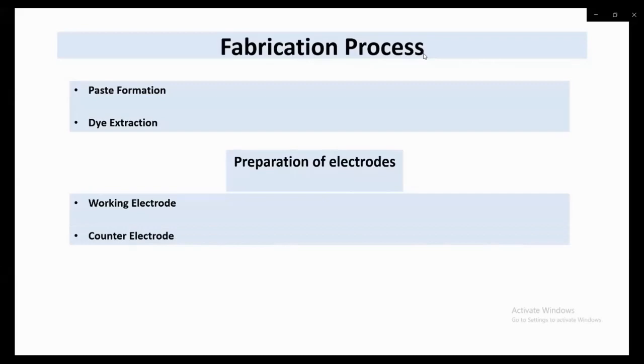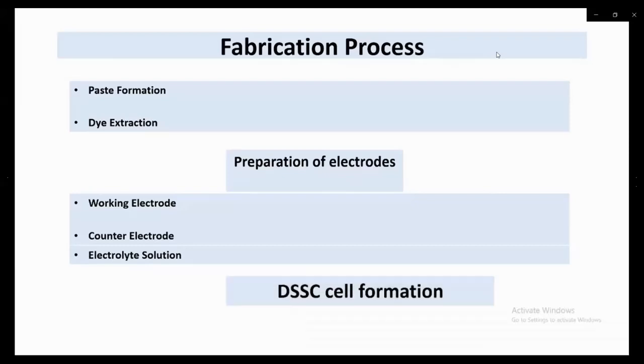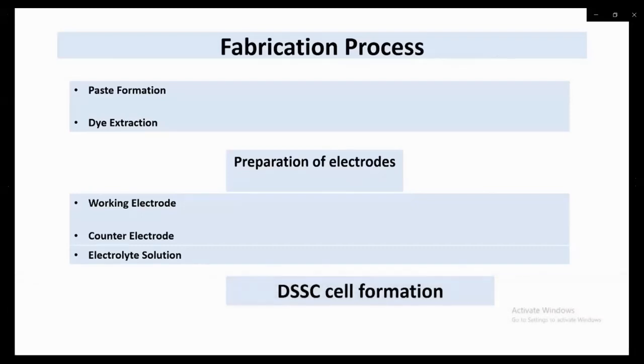The counter electrode was prepared using carbon soot. The electrolytic solution was prepared by taking 0.1 molar lithium iodide and 0.05 molar iodine in acetonitrile. The cell was formed by assembling the working electrode and the counter electrode with paper clips, with a spacer between the electrodes, and 2 layers of scotch tape were applied to the working electrode. Then 2-3 drops of the electrolytic solution were added between the counter and the working electrode. Then the slides were clamped together and the contacts were taken out. This is the process of forming the dye-sensitized solar cell.